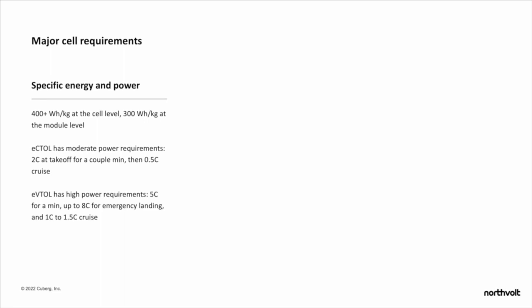This represents roughly a 50% increase from the best lithium ion modules these days, which are at about 200 watt hours per kilogram for aviation grade modules. So literally a 50% increase in how much you can fly. eCTOL, conventional takeoff, has, I would say, moderate power requirements, nothing crazy. Maybe something up to 1.5C or 2C for a few minutes at takeoff. And then you're cruising and using the lift of your wings for a very efficient cruise. So maybe 0.5C or even a little lower, 0.3C for cruise.